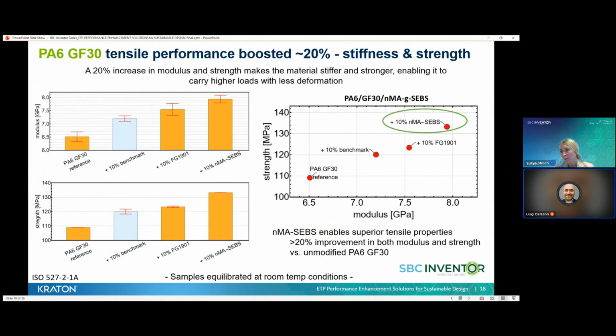If you could test a polyamide 6 containing 30% glass fiber immediately after molding, most likely the values observed would be somewhere in the range of 10 to 11 GPa for the modulus, and maybe 160 to 180 MPa for the strength, depending on the molecular weight that is used. Upon exposure to a moist environment, these properties will drop. And when the material is saturated with the equilibrium amount of water, typically the modulus will range between 6 and 7 GPa, and the strength between 110 and 120 MPa.